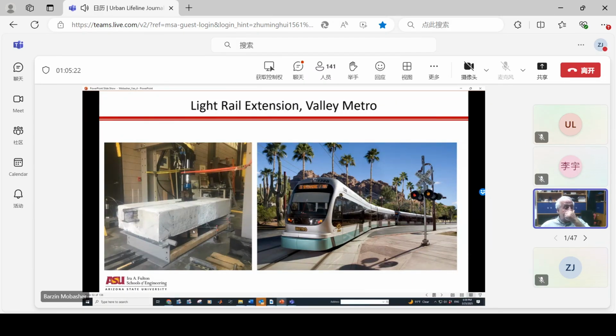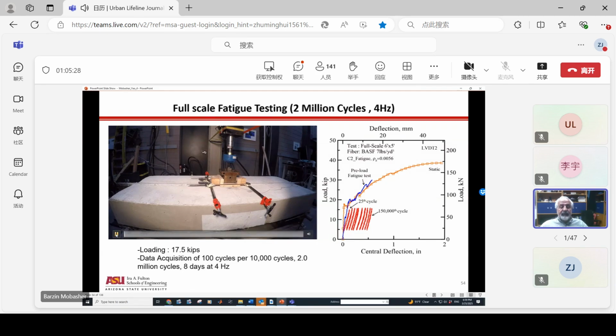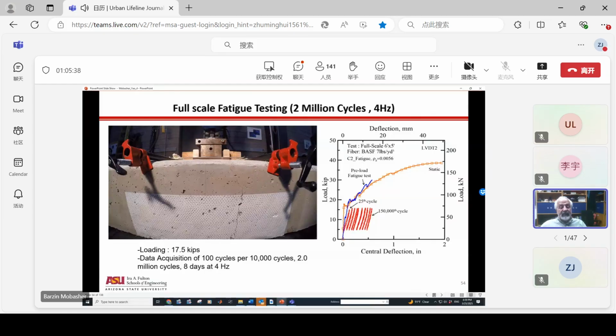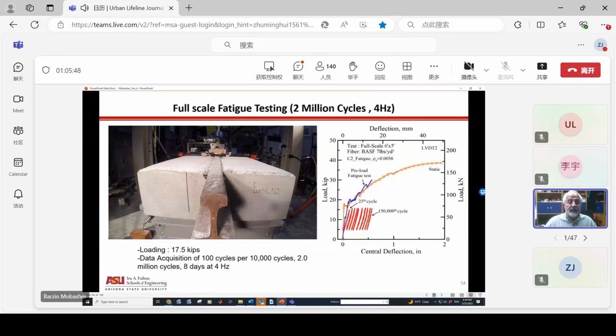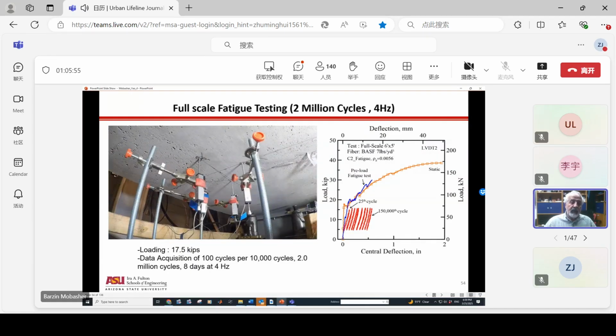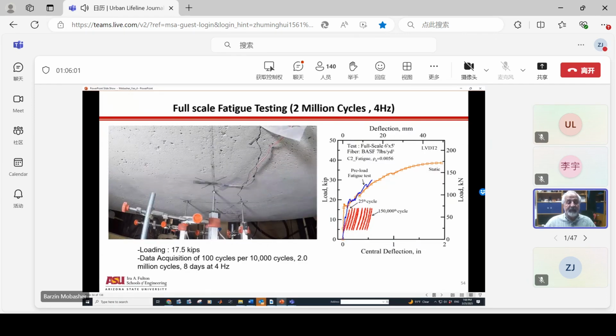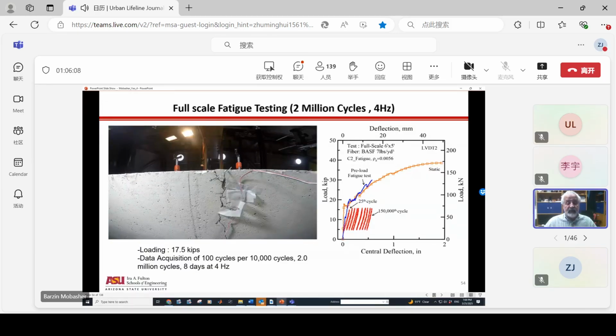Another project that we did was for our light rail system, Valley Metro, which allows us to replace all of the rebar with steel fibers, and we subjected it to 2 million cycles of fatigue. So first you crack it and then subject it to the fatigue situation of multiple loading. This would mean a significant amount of cost savings from the point of view of potential corrosion problem because of the DC current that exists, and that creates stray current corrosion. So if I take the rebar out and put fibers there, I have significantly reduced the risk. And this is 3 times the load that would be expected.